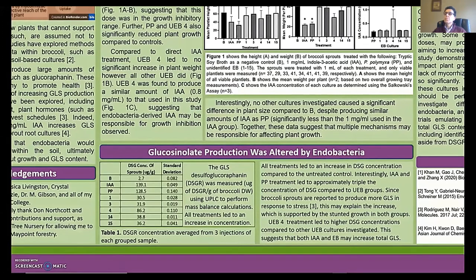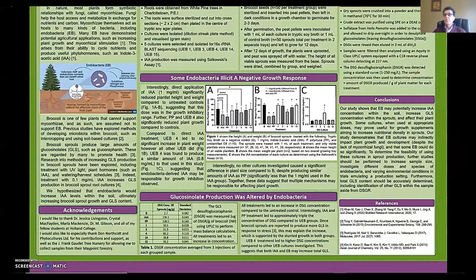Furthermore, the indole acetic acid standard and the P. polymyxa culture were able to increase the DSGR concentration to around 130 micrograms per gram, which is incredibly more than the UEB cultures. This is likely because the indole acetic acid used was actually within the inhibitory range, which would stress the plant, causing it to produce more glucosinolates. And the same can be said about the P. polymyxa culture. Our study shows that endobacteria are able to influence broccoli sprout growth through production of compounds.